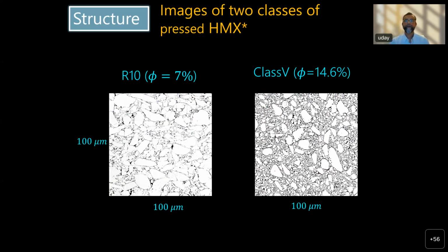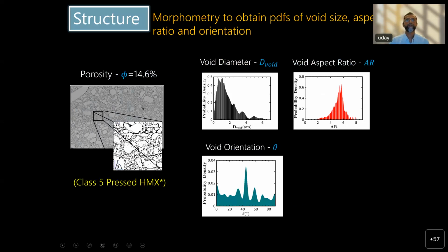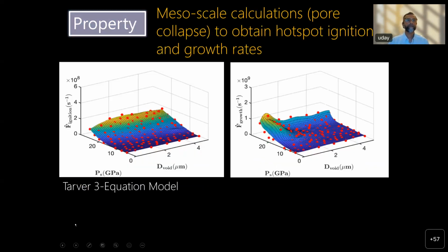Just to show an example of how MESSAGE works, the workflow of it. Suppose we have the microstructures, and these were provided to us by AFRL, Eglin, from Eric Welle and Chris Molek's group. So we have these pressed HMX microstructures, and we know their porosity, and we know the size of it. We can take these microstructures and analyze them to obtain things like the probability density functions of the void size, the aspect ratio of the voids, and the orientation of the voids in the material. Voids are the main features here that we're interested in. It's a pressed material, there's no binder. And so then we can take the statistics of the morphology, and that's the structure part.